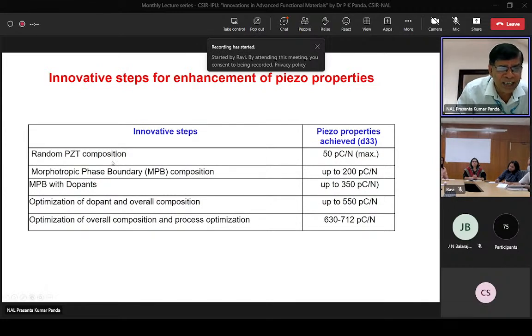And if you take a random PZT composition, you may end up with just 50 picocoulomb per Newton. But if you follow the morphotropic phase boundary, which I have shown, that will take you up to 200 picocoulomb per Newton. Then in the MPB, if you add some dopants you will be able to enhance it further, to 350 picocoulomb per Newton. And if you optimize the dopant addition, the type of dopant and the overall composition, it may go beyond 550 picocoulomb per Newton, and that has happened in our case. So from our experience, I am telling this at different stages of its development. Finally, optimization of the overall composition and process optimization led to the maximum value of 712 picocoulomb per Newton. This is the final composition which we have.